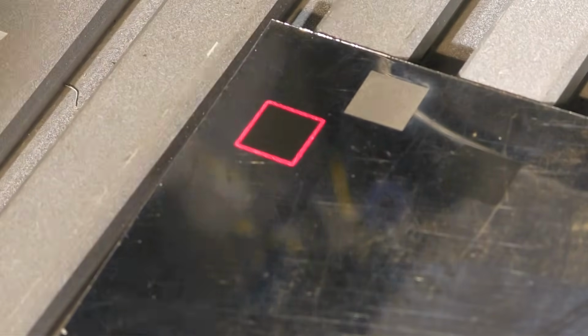You can actually see the scan speed this time. Now, two things I hope you'll notice. First of all, we've got some colour in there now, look. This one is a quarter of the speed of that one. So there it was silver, and now you're getting a hint of colour in it. Because what we've done, we've increased the power, and we're actually burning effectively the metal. We're producing a yellow oxide film on the surface.